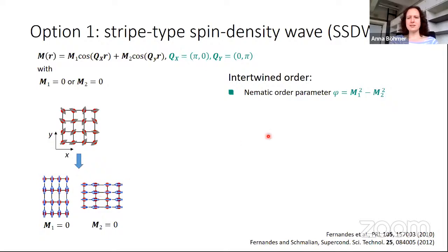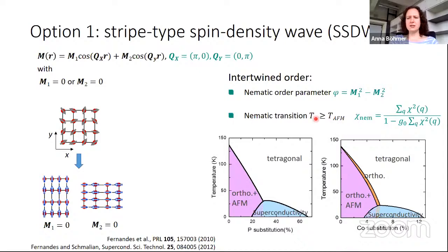I have either this one or that one, and that's exactly my nematic order parameter. Mathematically, this is 1 or minus 1, depending on whether you chose the left or the right option. And the name we gave for this, it's a new order, it's a new choice, it's an intertwined order of our magnetism. It's something higher order, something new, something emergent. And we already talked about nematic susceptibility. The point, and that comes from the theory, is we can find this nematic order parameter. It has to do with the magnetism, even if the magnetism itself is still absent. Or in terms of transition temperatures, we can find the nematic and structural transition at a higher temperature than the magnetic one. And we experimentalists already knew that. We saw it before. We have it in this phase diagram here. We find the nematic before the magnetic.